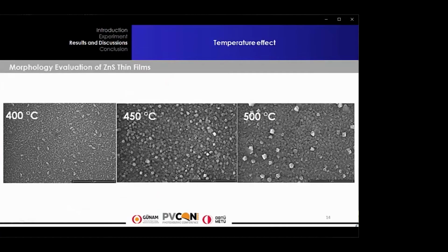The figure in front of you represents the morphology of the ZnS layers deposited by USCVD at different deposition temperatures. We can see that all the films exhibit good adhesion to the substrate, with very dense and very compact particles covering the entire surface of the substrate. The same images show the presence of a mixture of grains of hexagonal and cubic shape for the temperature 400 degrees Celsius, with a predominance of cubic grains toward high temperature. These results confirm the analysis obtained by X-ray diffraction measurements.